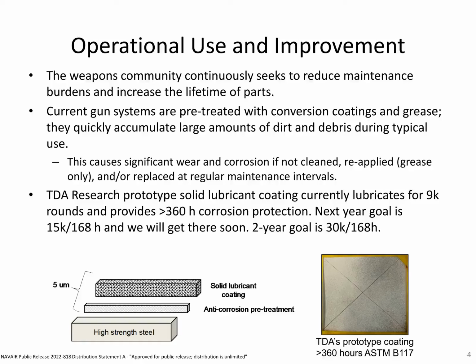So our goal, as I mentioned, is to hit 15,000 rounds as our initial goal. At the time of this presentation we had hit 9,000 rounds, we have now passed 15,000 rounds and 168 hours of salt fog corrosion. Should also mention that the 15,000 rounds is performed at 200 degrees Fahrenheit, which is the maximum temperature that the gun gets up to when it's continuously running.